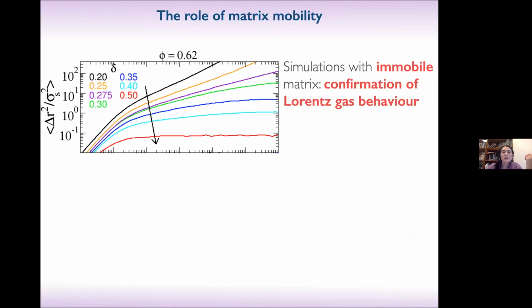We attribute this, differently from the Lorentz model, to the fact that our matrix is not immobile. So we performed the accompanying simulation also with an immobile matrix, and we find the confirmation of the Lorentz gas behavior. So we did simulations of large and small hard spheres at different delta, with the large ones at very high packing fraction that change in this way.